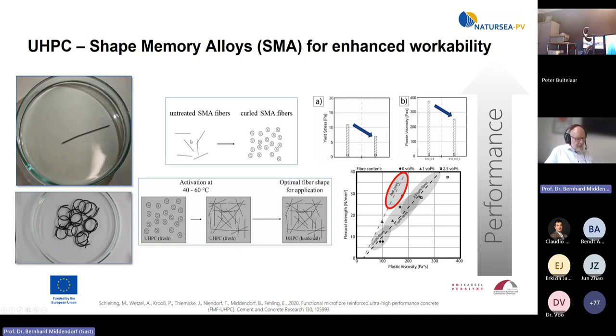We have heard from the presentations before that the fiber content of a UHPC is approximately 1.5 volume percent. Okay, you can do it till 2.5 volume percent, but then it is not workable anymore. But with this trick, with the shape memory alloy fiber, which we curl, you have the fresh UHPC, then you get a thermal impulse. The fiber goes back into its original state, and then you can add up to 6 volume percent of fibers into a UHPC, and this allows you to make the system you like to produce and to use in a building much thinner and lighter.